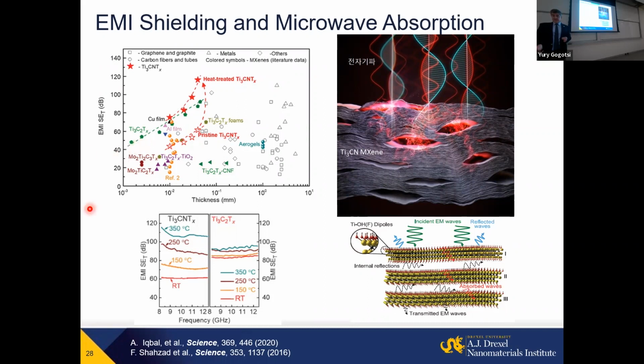And in this next paper, 2020, sorry, we showed that carbonitride MXene, which is less conducting than titanium carbide, outperforms, at the same thickness, even much more conducting metal like copper. So it really opens the opportunity to look at the interaction between electromagnetic waves, which have centimeter wavelengths, like in the X band shown here, and 2D materials, which no one had studied carefully before. And the effect of this discovery on the field was such that this 2016 paper in Science, within 5 years, became the most cited paper ever in the entire electromagnetic interference shielding field, which is, of course, a very old and established field where a variety of carbon materials, graphene, nanotubes have been explored. You see how disruptive the arrival of new materials can be to a field.